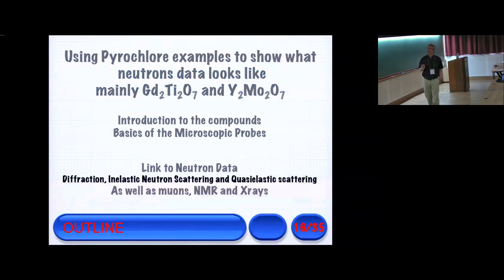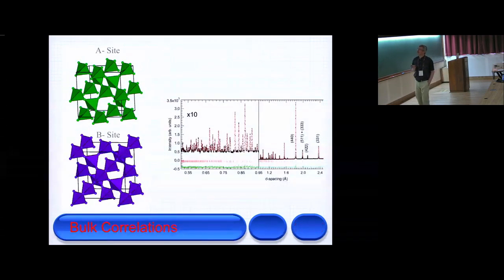So I'm going to now try and use the pyrochlore gadolinium titanate and yttrium molybdenum oxide to talk about a few of these probes. Neutrons I've covered in a little more detail because that's what I'm an expert at. But I find, especially in frustrated magnets, you need more information. It's very, very hard in any frustrated magnet to get the full story from just one probe. So here, diffraction will give you the bulk structure,